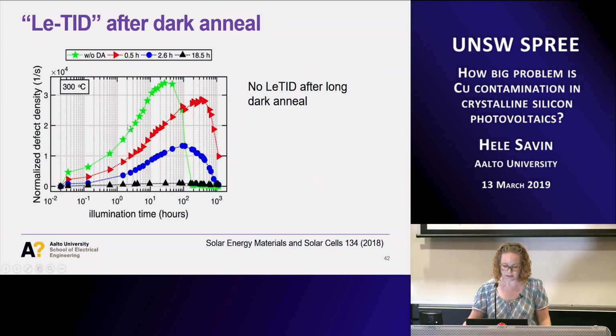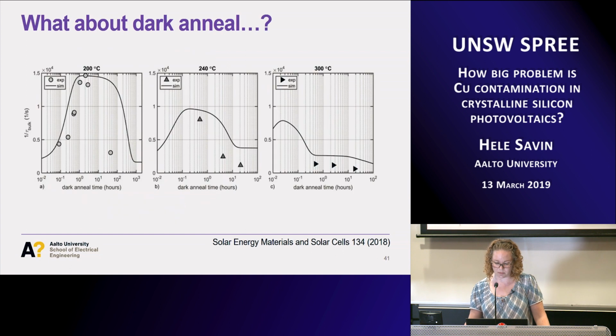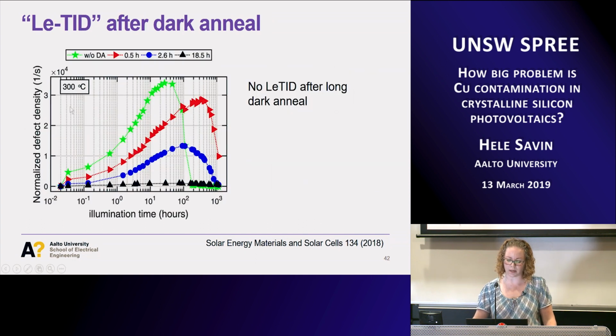So the longer we wait, and these are the different curves now with different annealing times, half an hour, 2.6 hours, or 18.5 hours, we clearly start seeing less and less degradation, and you actually have to wait quite a long time, 18.5 hours, to reduce the light-induced degradation. You can do the same thing with these temperatures, but then the annealing times become maybe too impractical. So that's why it's better to go to a higher temperature. Okay, this is still relatively high temperature, but still quite okay.